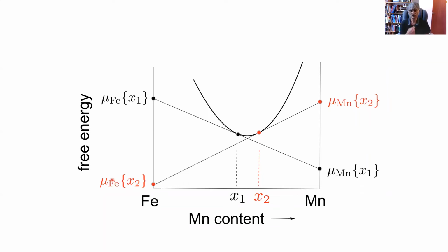Okay. Now, notice in this case that the chemical potential increases as I increase the concentration. Okay. So we write that the change in the chemical potential with the concentration is greater than 0. So we have a positive value of d mu by dc, how the potential changes with concentration. But you will know from your undergraduate lectures that we can also have a curve which is of this shape, where when I increase the concentration from x1 to x2, the chemical potential actually decreases.